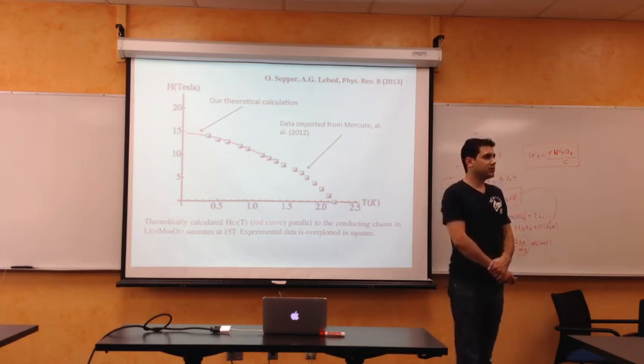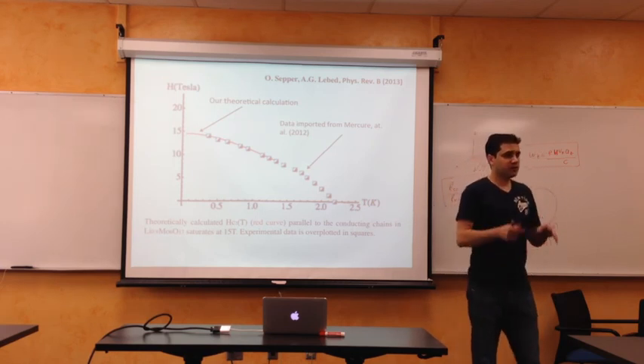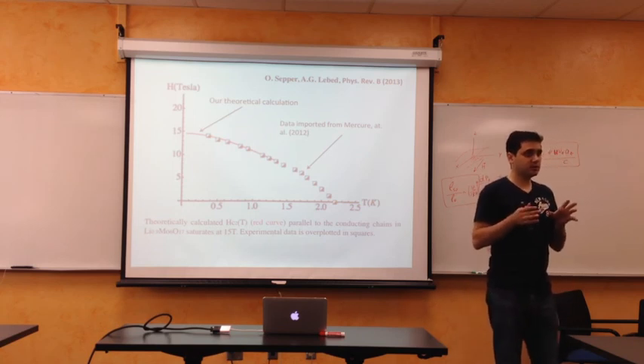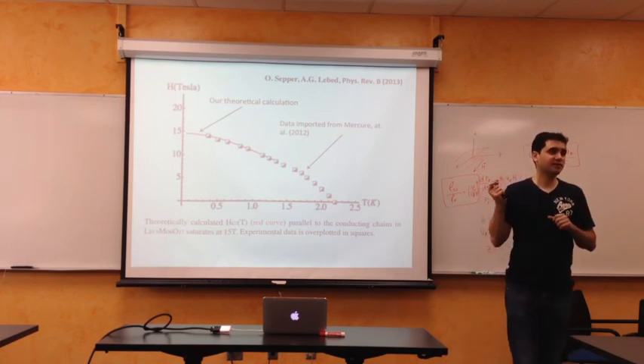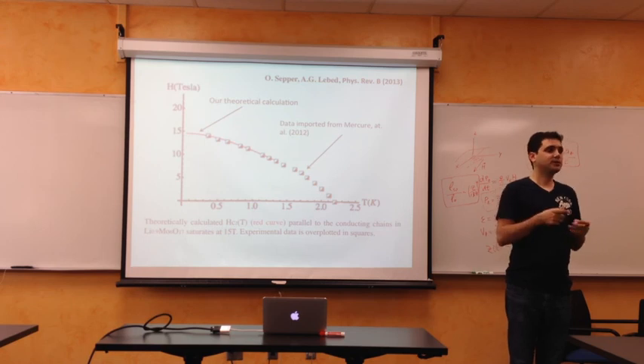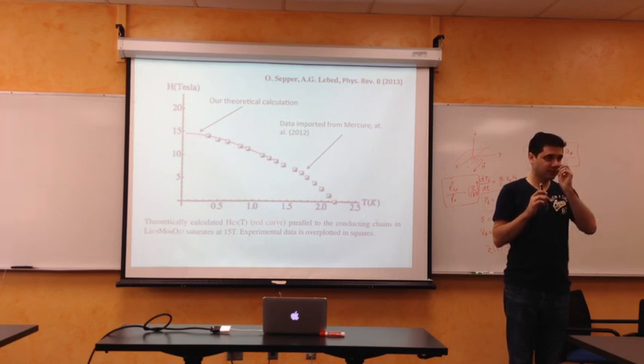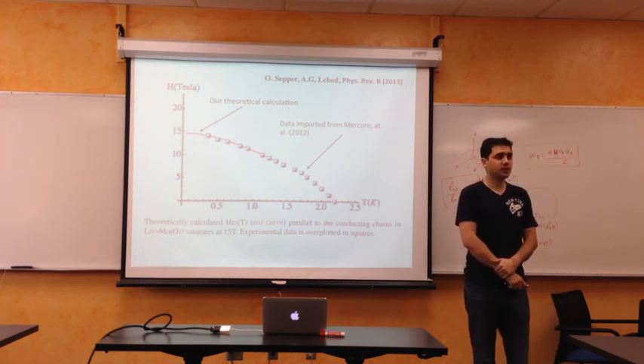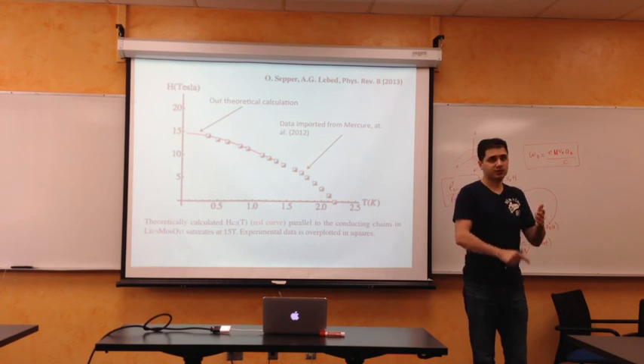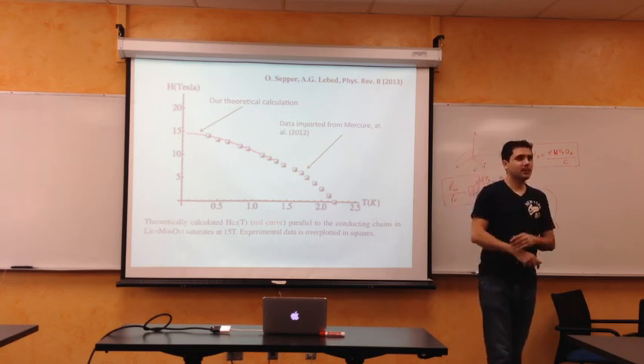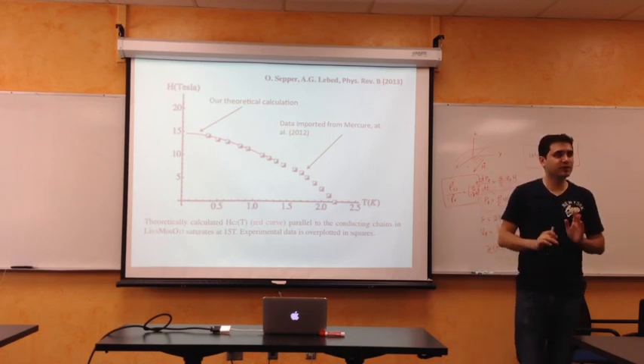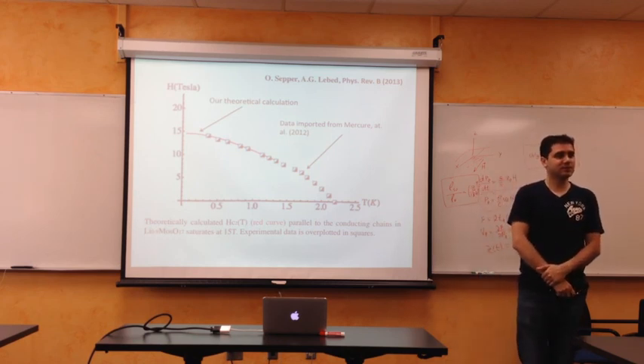The singlet and triplet pairing can be thought of as competing phases. At very high fields, triplet pairing would be preferred because it's not sensitive to the paramagnetic spin splitting effects. You can think about it this way. Because the superconductor shows such a huge discrepancy in magnetic fields, it's a strong candidate for such a type.